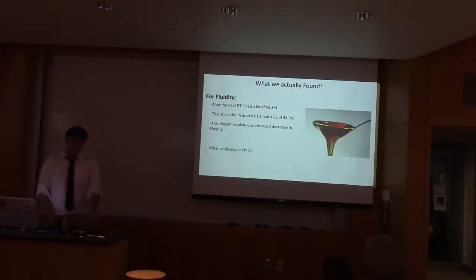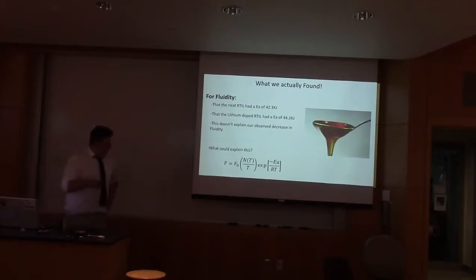So we have to ask what could explain this. Well, if we go back to our equation, which I've been told is what we should be doing always when we run into a problem, we imagine that if the EA is not changing significantly, the only thing left to change is the exponential prefactor. This means that the difference between the viscosity of our solutions is caused by a change in the exponential prefactor.